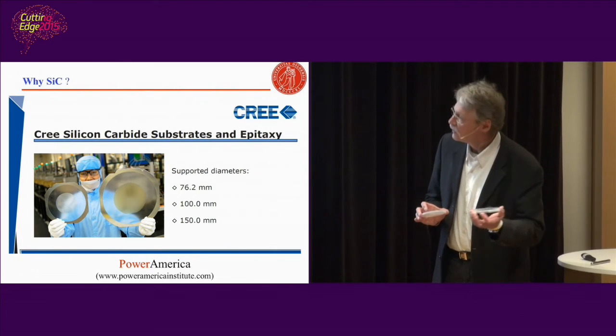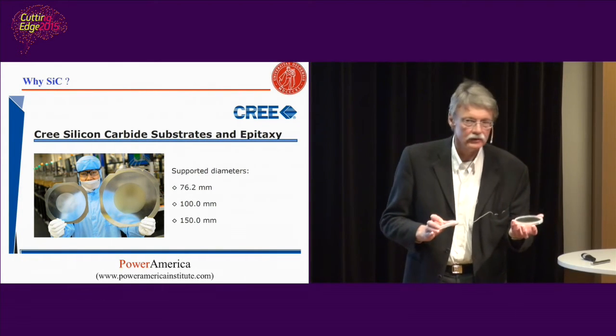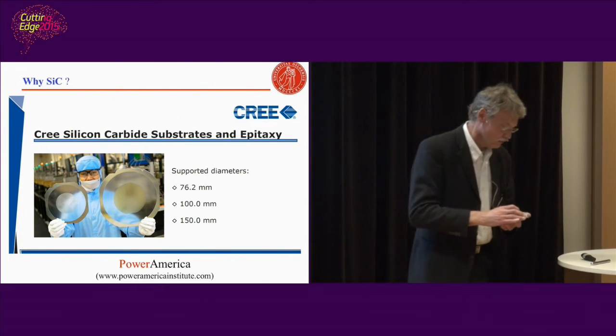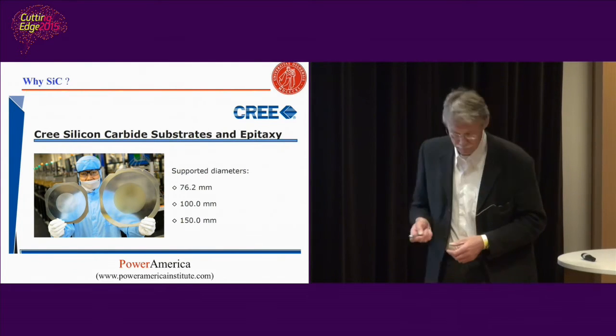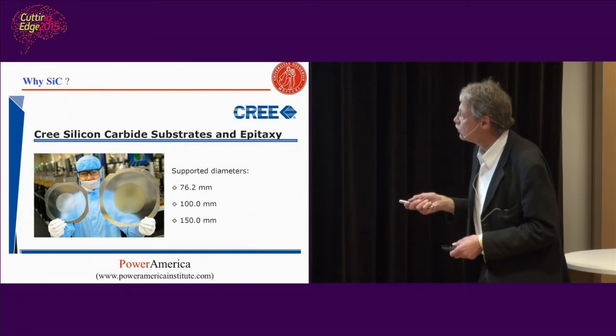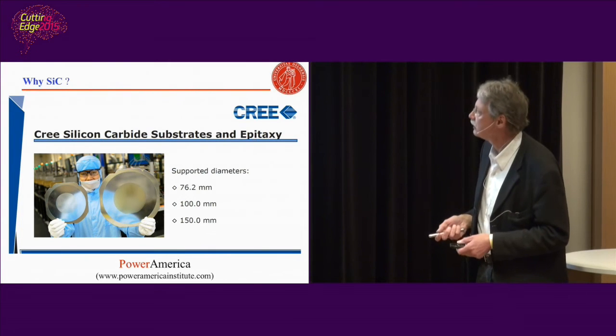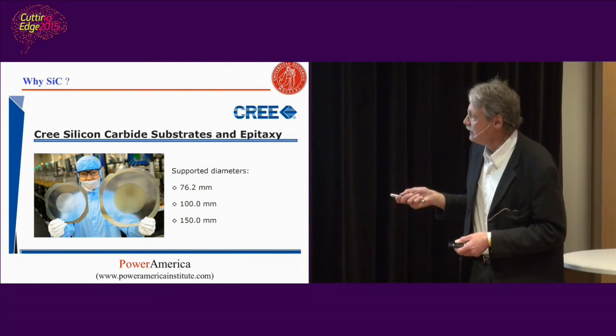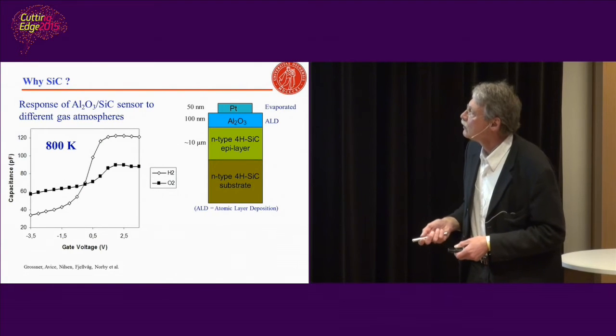What we do have today is that we can actually commercially buy silicon carbide wafers with a diameter up to 150 mm, which I think is next after silicon is the biggest semiconductor wafers you can have. They are a little bit more expensive than silicon. This is what we use in our lab - this is a 100 mm wafer. If you take a silicon wafer of this size, it would be maybe a few hundred Norwegian kroner. If you take this one, maybe you have to multiply that by 20 - let's say 5,000 Norwegian kroner. So it's a little bit more expensive. But you will see at the end, we will gain. The big players, the companies, they are now in the 150 mm area. We just came back from a silicon carbide conference last week, and in 2018 there will be 200 mm wafers available.